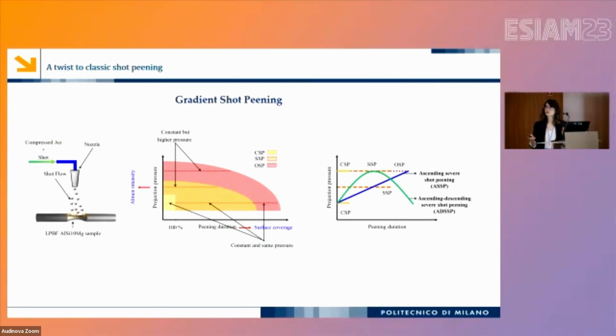So with this gradient shot peening, what we did is that we continuously change the pressure during the process. With different strategies, we considered, let's say, this ascending severe shot peening. We are always at very high Almen intensities, but we are starting from an intermediate Almen intensity and going up to a high one. Another strategy was ascending-descending severe shot peening. So we are starting from an Almen intensity that is used by conventional treatments, going to a much higher Almen intensity, and then coming back to the original value.